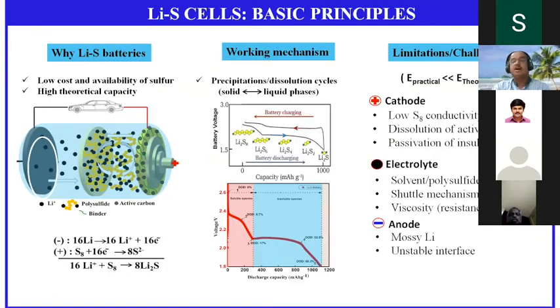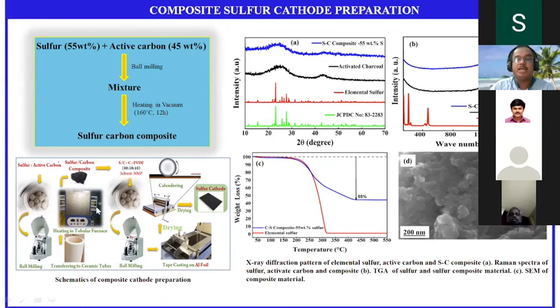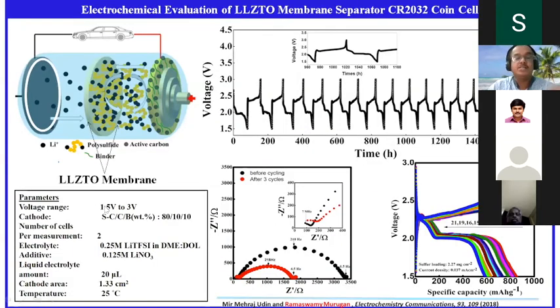People struggled hard. If you ask me, everywhere we have problems: from the cathode, low sulfur conductivity, dissolution of active material, passivation, instability of Li2S. In the electrolyte also, solvent and polysulfide reactions, shuttle mechanism, viscosity variations, and at the anode, mossy lithium and unstable interface. That's why this initially took a very big leap, then slowly it's coming down. Again, if you want to improve the performance, we have to think about making a solid electrolyte. For this, we made an LLZTO membrane, and we were able to demonstrate that we can barricade this shuttling mechanism with solid electrolytes.